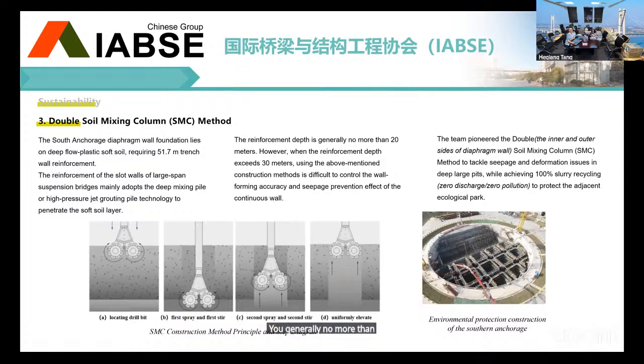However, when the reinforcement depth exceeds 30 meters, using the above mentioned methods, it is difficult to control the wall forming accuracy and the seepage prevention effect of the continuous wall. The team pioneered the double soil mixing column method to tackle seepage and deformation issues in deep large pits, while achieving 100% slurry recycling to protect the adjacent ecology park. Zero discharge, zero pollution.